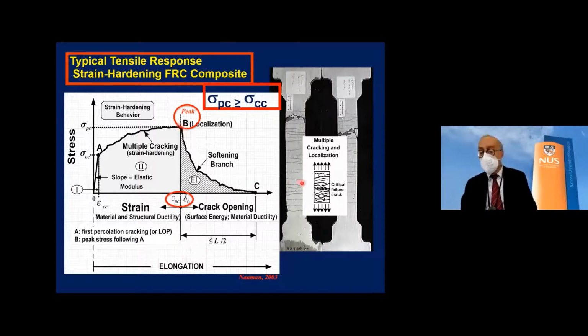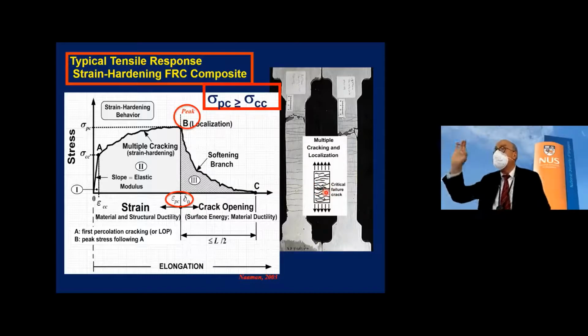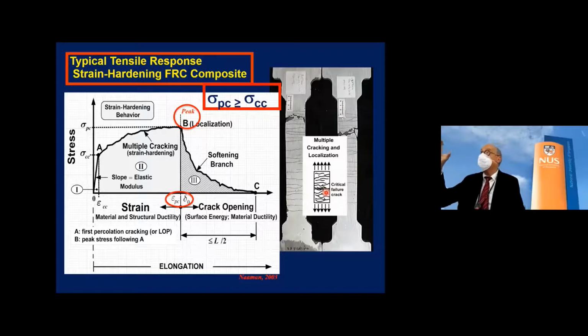That is, one of the cracks becomes weaker. Imagine you have a chain and one link starts opening. That's localization. And then the specimen's response softens over what we call a softening branch. That softening branch is accompanied by either fibers pulling out or fiber failures or a combination of both.